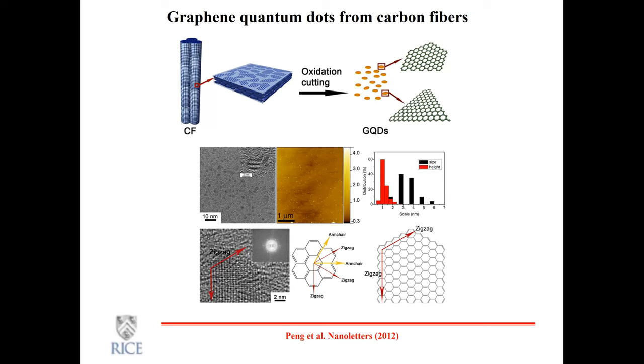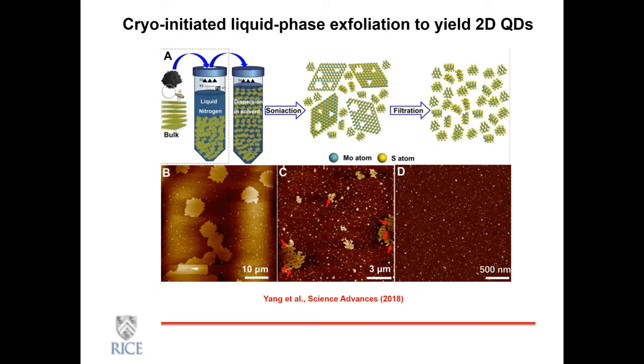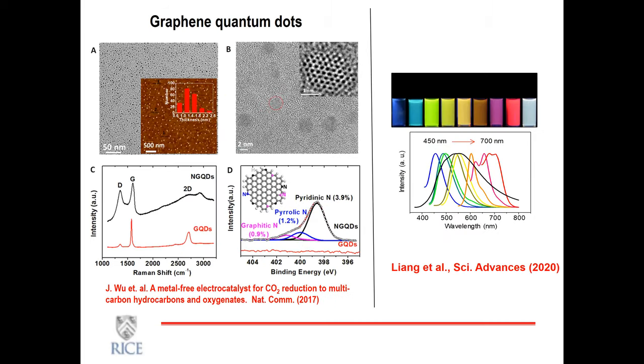carbon dots. This is an area where significant work has been done in the past decades. People can now not only select quantum dots made of graphitic carbon, but also do this in pretty high yield. This is a technique that we designed, a cryo milling or cryo processing technique, where because of the mechanical properties at low temperatures, you can break up these materials pretty well and get a very high yield of quantum dots. And these quantum dots have been very, very useful in applications.